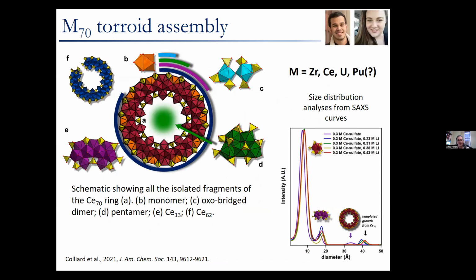So one way that we've been looking at these tetravalent metal clusters and other similar structures is through the assembly of this M70 toroid, where M is the metal zirconium, cerium, or uranium. This was a great demonstration of not only being able to synthesize the parent compound, which is M70, which is really great, but we are also interested in the mechanisms of formation. So how does this form and precipitate from solution? What are the building blocks?